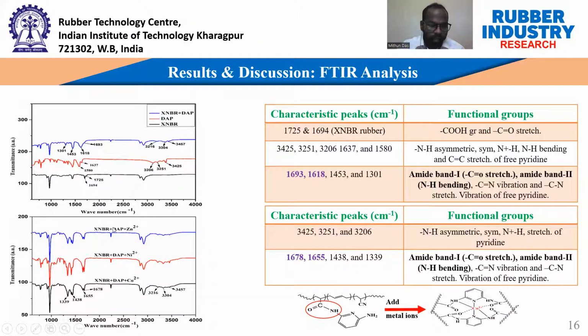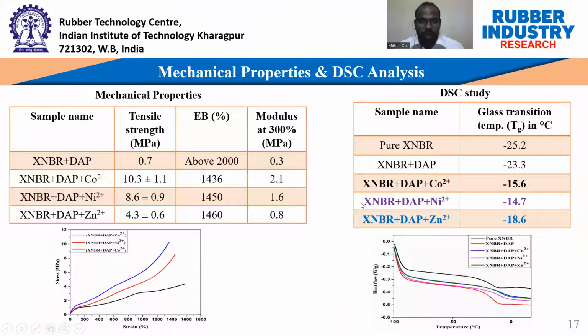And after the addition of various metal ions, these 1693 and 1618 peaks shifted to 1678 and 1655, mainly because of the formation of various metal ligand coordination bonds inside the rubber matrix. The same thing also happened in the case of the nickel system and the zinc system. From the FTIR analysis we understand the formation of the amide linkage and also the metal ligand coordination bond inside the rubber matrix, and then we performed the mechanical property tests.